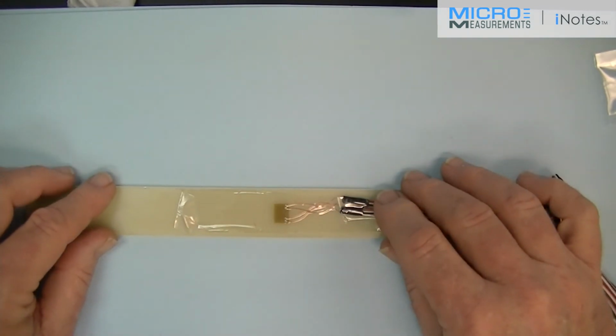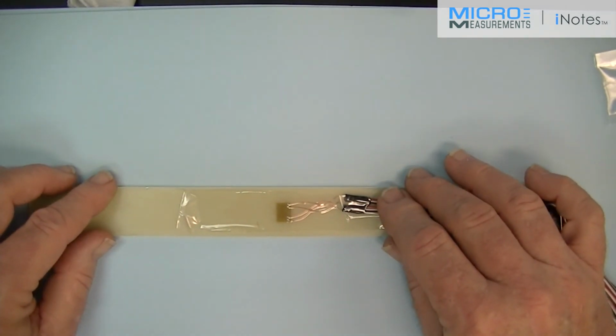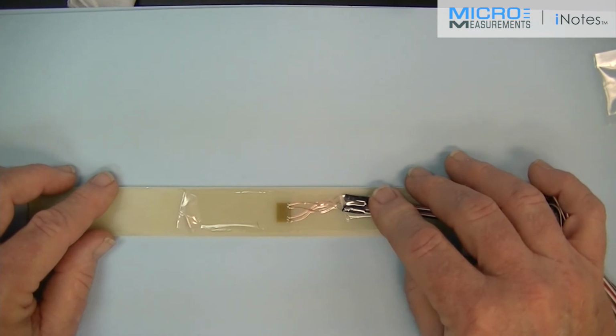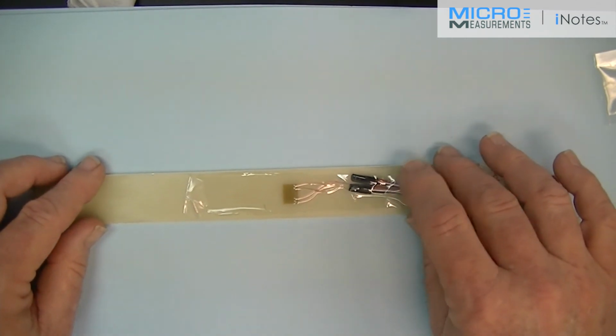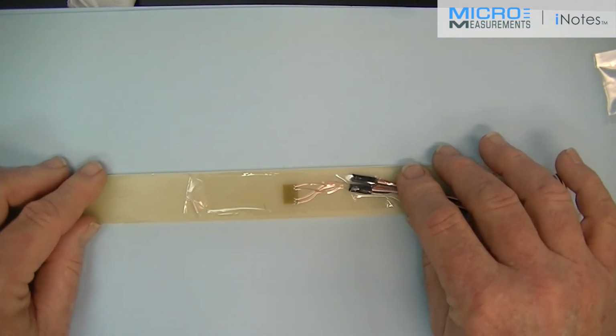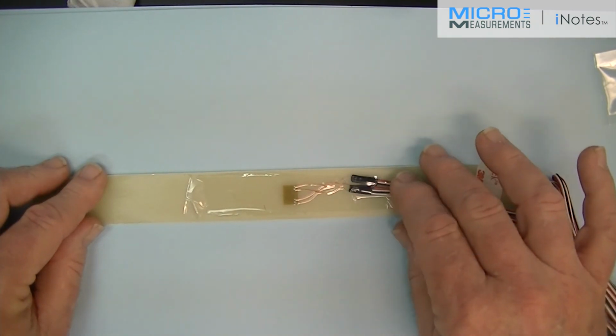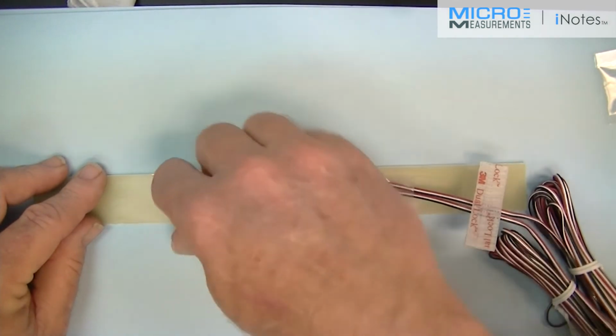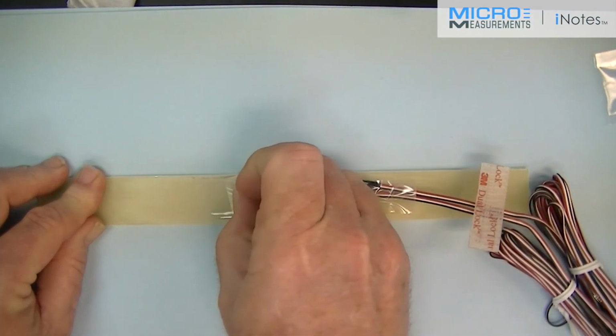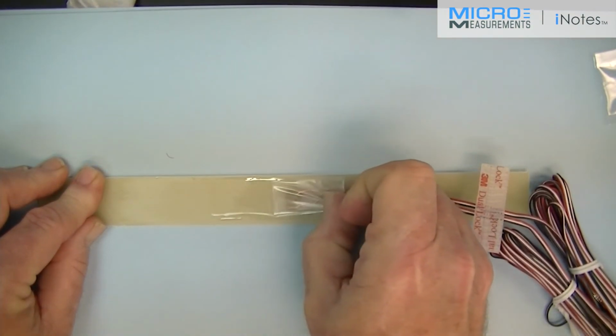Before, we peeled the tape up at a shallow angle. Now we're going to pull it at 180 degrees back on itself. The adhesive system is excellent in shear, but not terribly good in peel, and so we want to remove the tape and put the adhesive system into shear while doing so. So you can see I'm going to pull the tape 180 degrees back on itself.